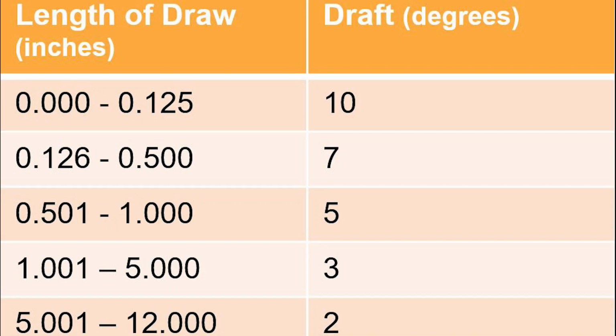And then draft is another thing to consider that you don't really need in machining, but you definitely need in casting. If you need a straight 0-degree draft, that's going to have to be machined, or you're going to have to cast and machine down to the 0-degree draft. Another thing to consider is flatness. How much flatness is required, and how big of a surface is it? You can do secondary machining operations to hit those after casting if you have that near net shape, but it's factoring in all of the different factors of your complexity, the size, and how many you're manufacturing.